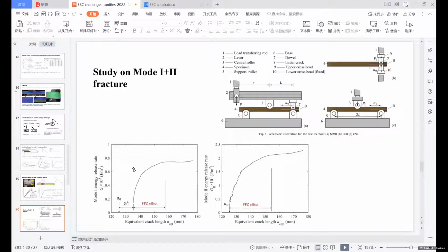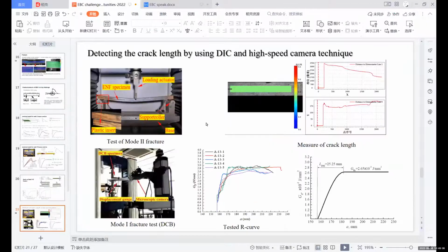So sometimes there is mode 1 plus mode 2 fracture. So this picture shows how to study the 1+2 hybrid fracture. We also developed a method to get the energy resistance curve for these fractures. So this is detecting crack length by using DIC and high-speed camera technique.